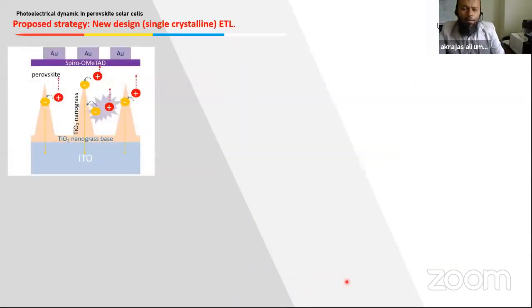So if we look at the devices using the nanograss TiO2, we can see the description from this model. The nanograss will provide us with a highly ordered porous structure, no dead end pores, so we can have large area contact with perovskite, where charge separation and charge transfer can occur anywhere on the body at the interface between nanograss and perovskite. Then, because the nanograss is single crystalline, the coupling based on the nanograss is very good. So we may have facile transport and extraction to the external circuit.